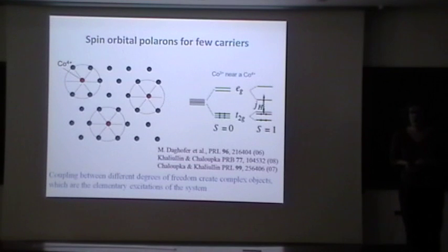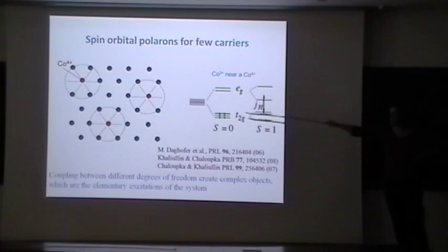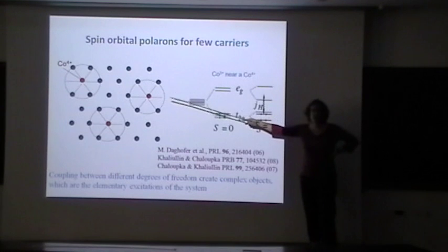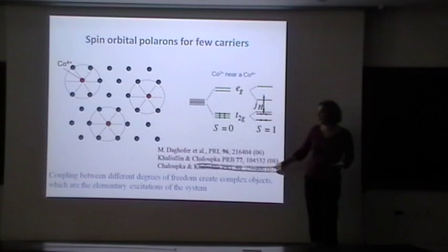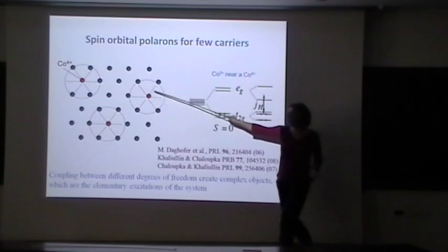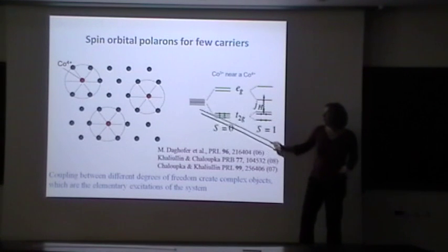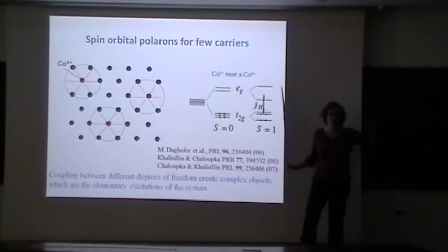Is that general picture consistent with the NMR? No, fine. So it's not easy to answer. I mean, the one problem with this picture is there has never been any direct observation of magnetic cobalt 3 plus. Now, this picture is very naive, telling you that this will really be stabilized at a static level. So it could also be some excitation. In fact, what they discuss in this paper is that when you have a cobalt 4 plus that goes from one side to the other, you will create these states as some vertical excitations. And so in this case, it's not really easy to know what you would observe on the NMR time scale.